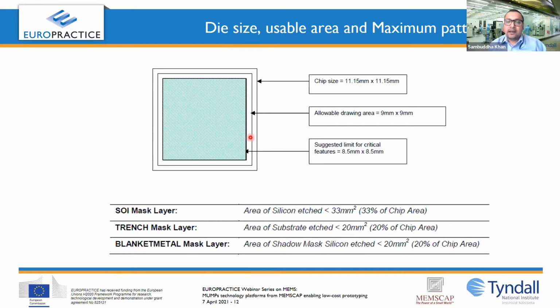Each SOI MUMPs device or die is 11.15 mm by 11.15 mm, so almost like a 1 centimeter chip. Now, a designer cannot use the entire area for designing. You need to leave some space around. So the allowable drawing area is 9 mm by 9 mm. And it is suggested that all your critical features, meaning the smaller features that are very crucial for your device performance, be within an 8.5 mm by 8.5 mm area.